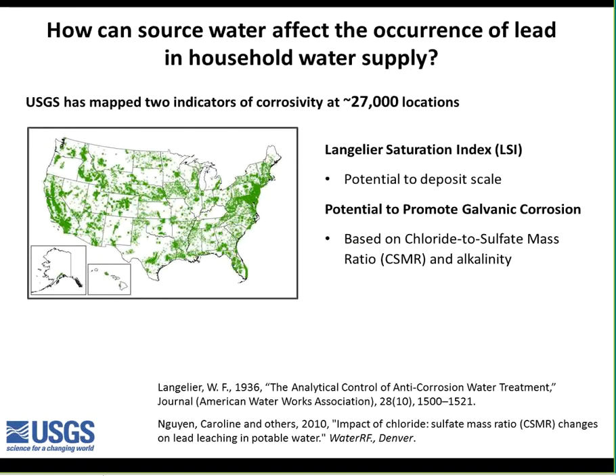Furthering this question of how source water can affect the occurrence of lead in household water supply, the USGS has mapped two indicators of corrosivity at about 27,000 locations shown in green on this map. The two indicators are the Langelier Saturation Index, or LSI, and the potential to promote galvanic corrosion. The Langelier Saturation Index is a measure of calcium carbonate saturation and therefore a measure of the potential to deposit scale. The potential to promote galvanic corrosion is based on the chloride to sulfate mass ratio, or CSMR, and alkalinity.